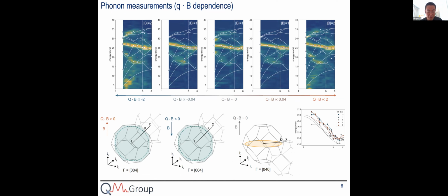But for some exotic phonon features, we also want to measure how it changes when you flip the polarity of this magnetic field, from positive polarity to negative polarity. And because of the crystal symmetry, it does not quite have an asymmetric field-induced phonon dispersion change. But if you really look at how certain branches of the optical phonons change as a function of Q dot B, it actually develops a level of asymmetry. For example, along certain directions they flip sign, which means one becomes higher and one lower, or along certain other directions it also becomes higher in energy. So in some directions it can be harder, in other directions it can be lower.